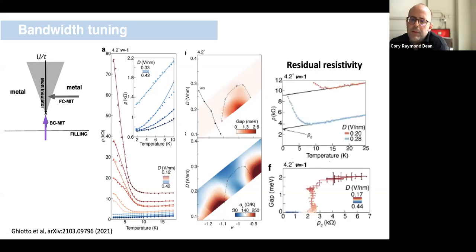One of the peculiarities that we identified is that if we look at R versus T behavior at half filling, then you can see here, as I indicated in the previous plot, there's a well-defined linear dependence at temperatures above which we have the insulating state. So the insulator at low enough temperature gives way to this T-linear behavior. And what we observe is that if we bandwidth tune in and out of the Mott gap, so if we have a displacement field value where there's a well-defined gap or there's not a well-defined gap, then we can identify this parameter, which we call the residual resistivity, where we project this linear T behavior to zero temperature and ask what's the residual